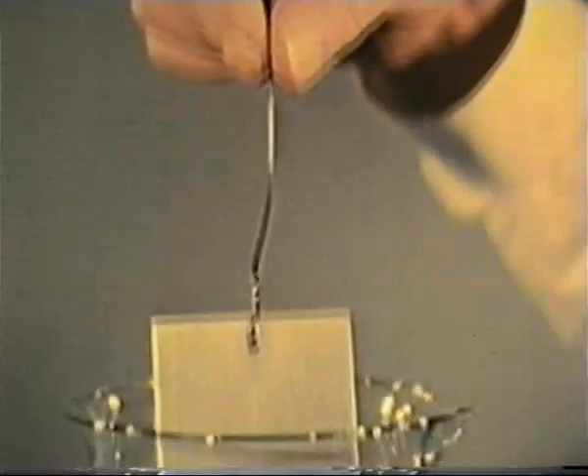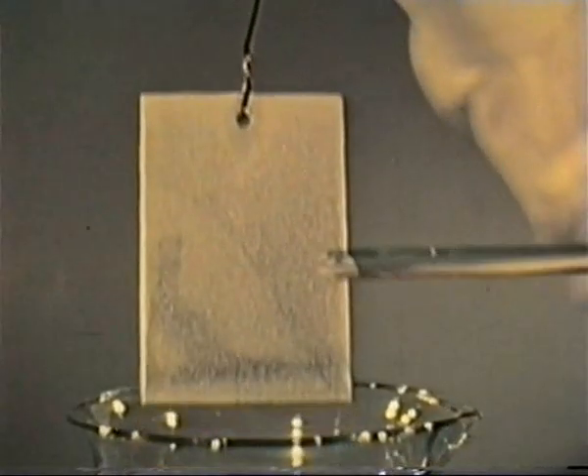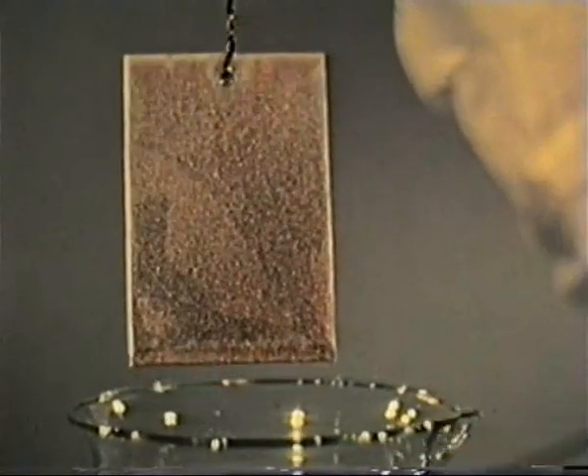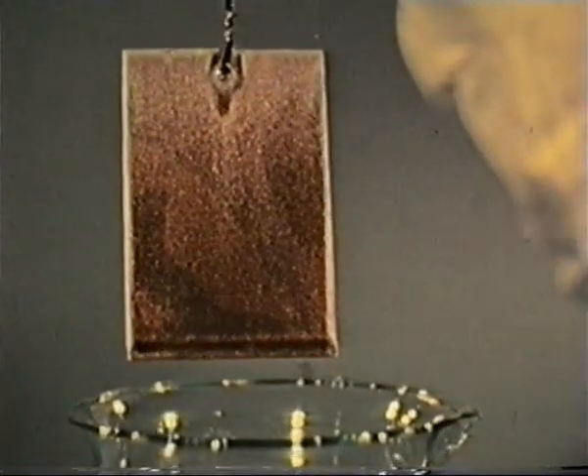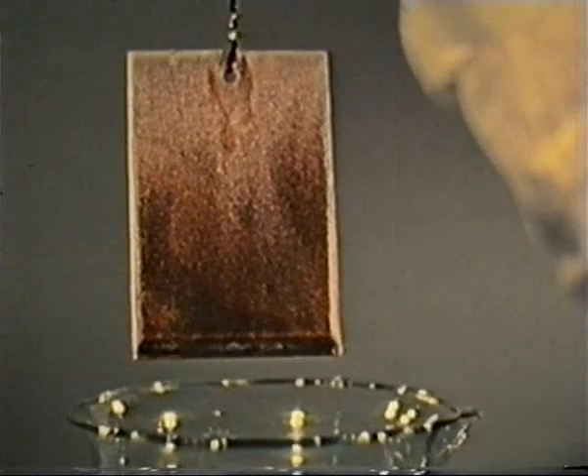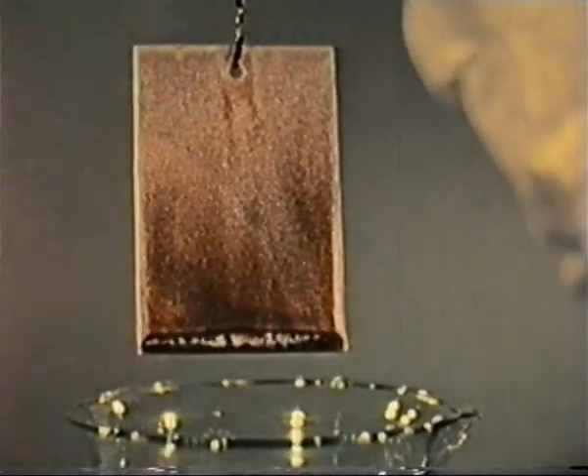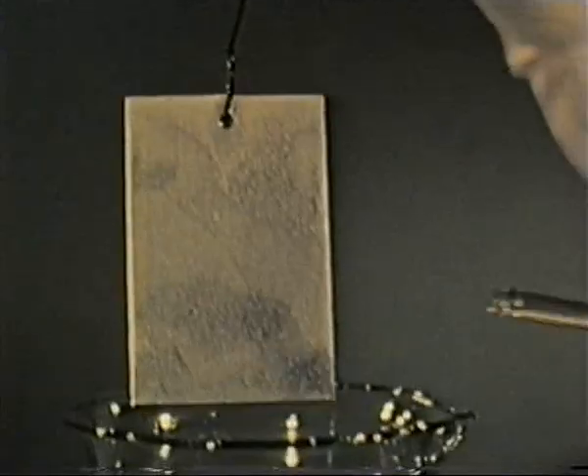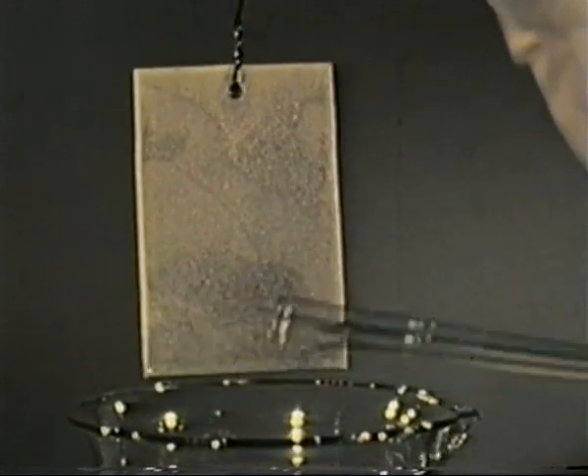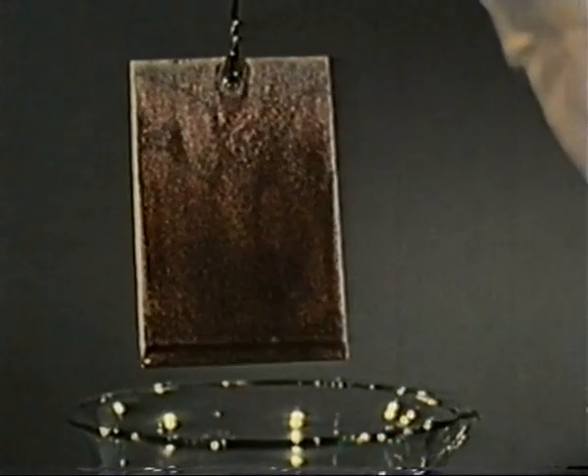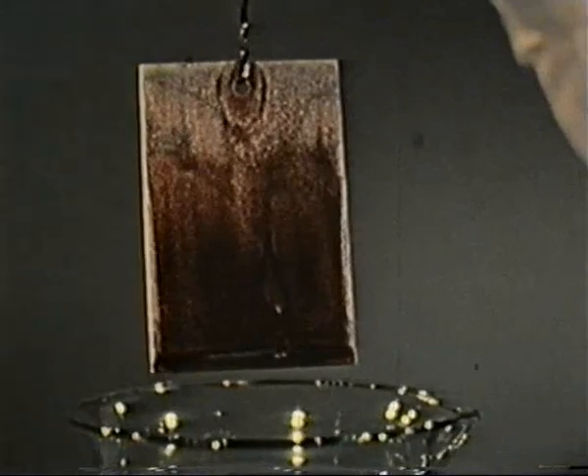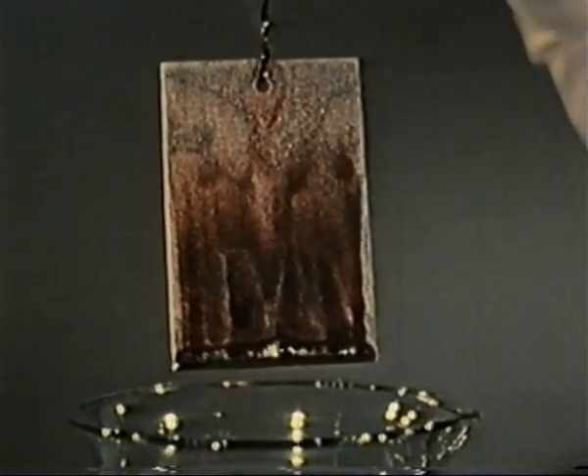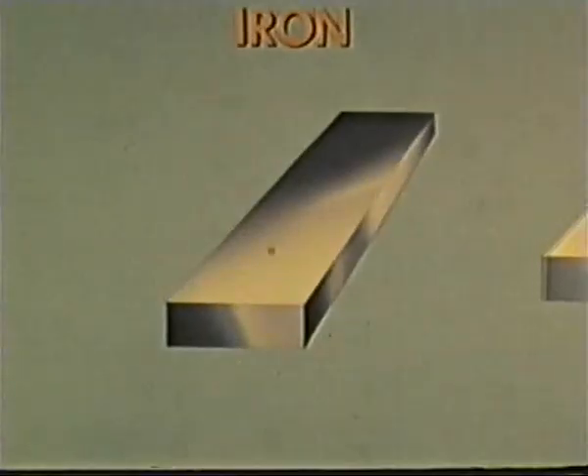In slow motion, we can see that copper plates out radially from the point where the film is broken. An active area at the point of impact becomes anodic to the surrounding passive area acting as a cathode. The reducing action at the cathode destroys passivity and corrosive action spreads. This type of unstable passive film is obviously not a dependable means of protecting iron against corrosion.